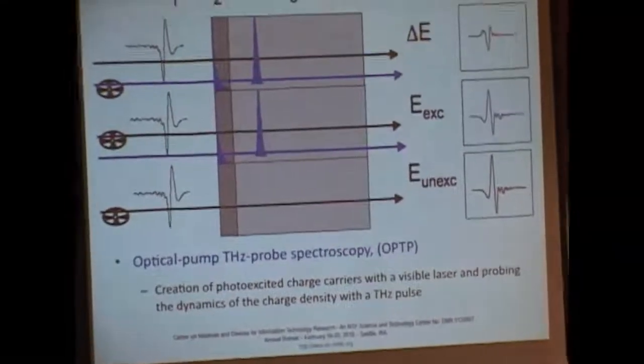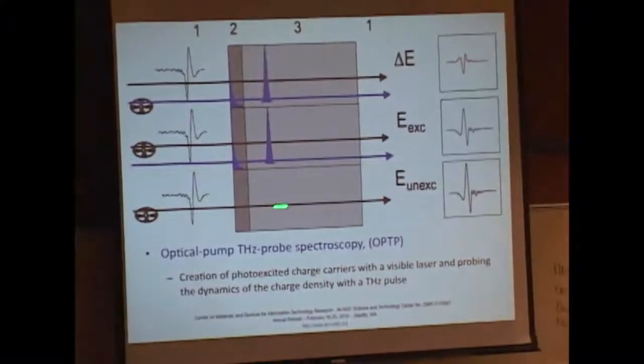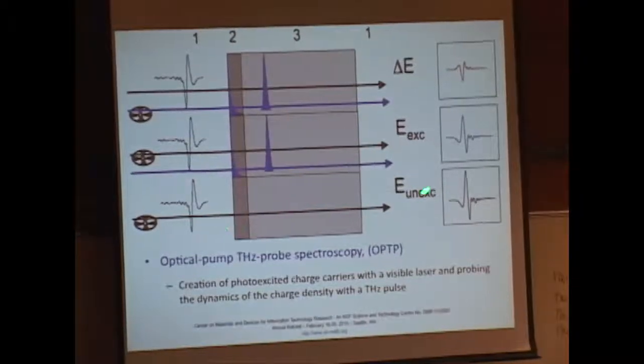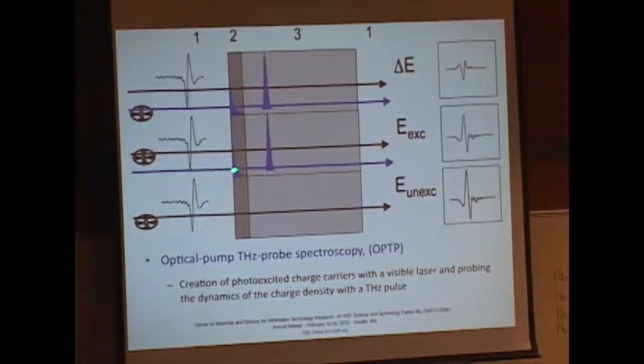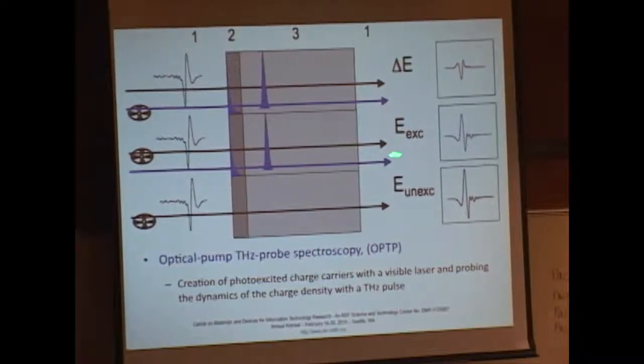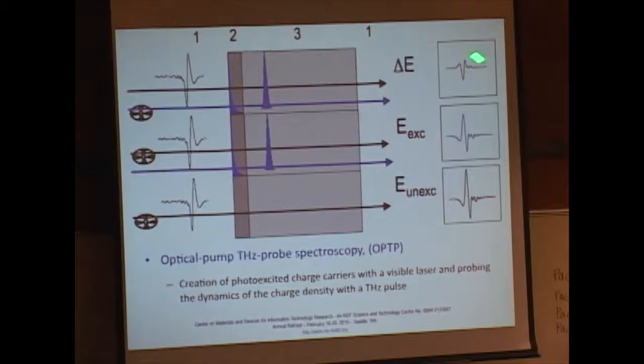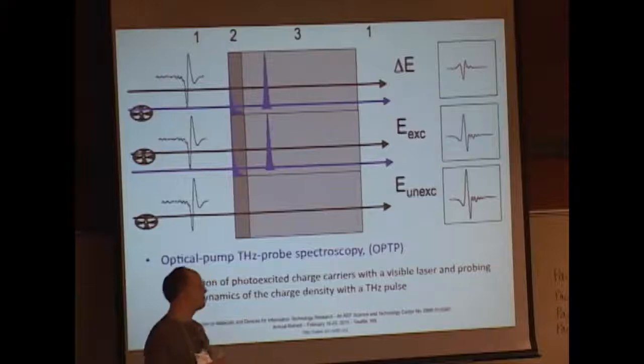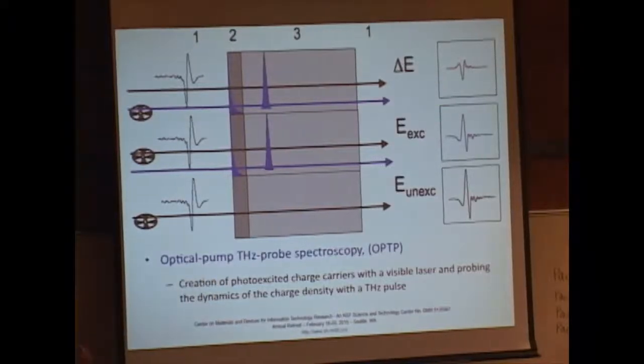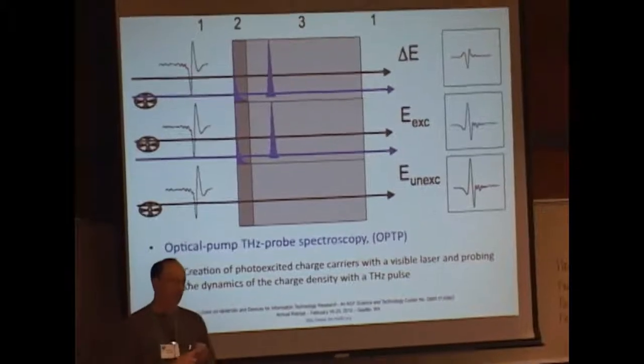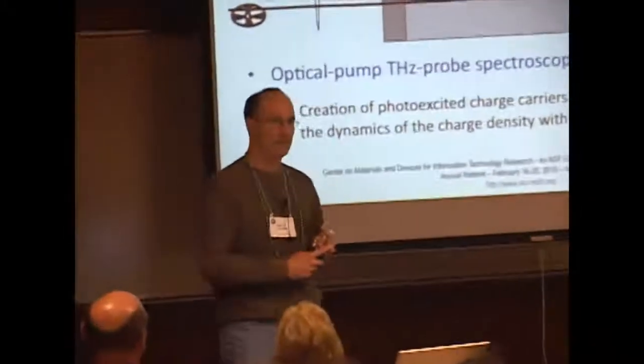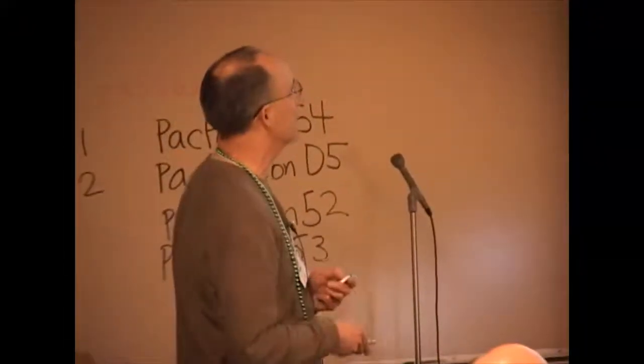And that process is similar to what I showed you before. We look at what happens when the terahertz pulse goes through the material, and we call this the unexcited state. And then we excite the material, create some charge carriers, and send a terahertz pulse through, and get two different traces. If you subtract those two, you would get this. You can actually get this one directly if you modulate the pump beam. And this thing here is directly proportional to the amount of photoconductivity, and we get the real and imaginary part from this coherent detection. If you model this then, you can extract things like carrier mobilities, charge concentrations, and efficiencies. And this hopefully will be of some value to people who are making new materials in this area.